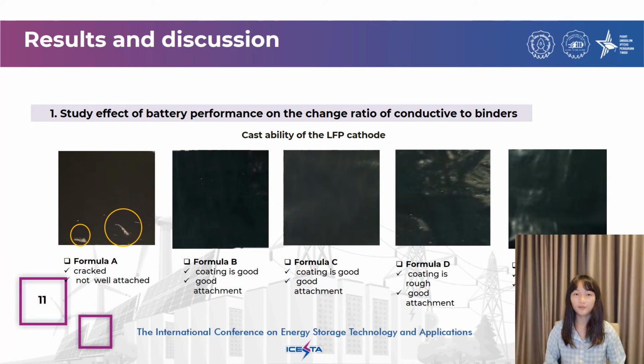This slide shows observation of the castability of the LiFePO4 cathode using different ratios of conductive to binder. The external characteristics of the surface coating of formula A to E were recorded and noted. The pictures were taken with a phone camera, which may not show as much detail as microscope inspection would. Formula A, with the lowest amount of binder, has slightly cracked on the surface. The yellow circle indicates where the crack can be clearly seen.